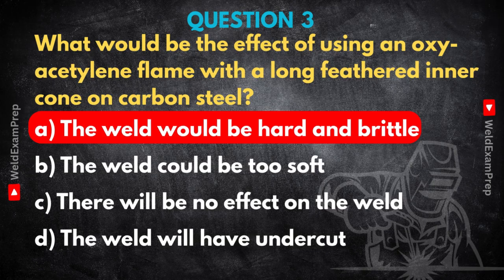Hard and brittle. Okay, what is it about that long feathered inner cone that causes this? That description, long feathered inner cone, is the visual signal for what's called a carburizing flame. It means there's too much acetylene gas compared to the oxygen. Got it. Too rich, like a fuel mixture. Precisely. And that excess acetylene breaks down in the heat, releasing free carbon atoms directly into the molten weld pool. This extra carbon gets absorbed by the steel.